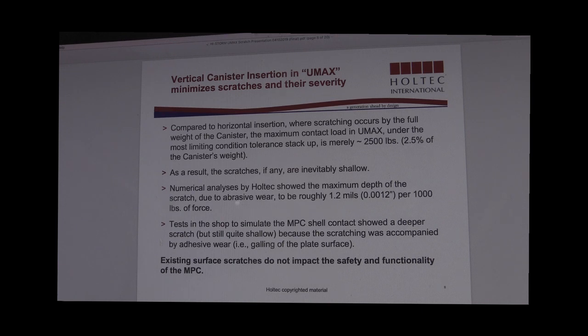When you look at the UMAX system and you consider the inside diameter of the HI-TRAC as well as the UMAX storage module, the maximum feasible rotation of the MPC is very small, on the order of 1 degree. So with such small rotation angles, it really becomes physically impossible to have a very large lateral contact force between the MPC and the internal features of the UMAX system. And that's why we conclude on the slide that the maximum contact force, even under the worst hypothetical configuration of the MPC, is still only on the order of about 2.5% of the canister weight.